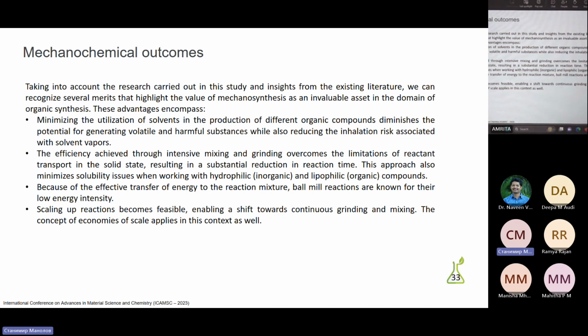The efficiency achieved through intensive mixing and grinding overcomes the limitation of reactant transport in the solid state, resulting in a substantial reduction in the reaction time. This approach also minimizes solubility issues when working with hydrophilic and lipophilic compounds, and because of the effective transfer of energy to the reaction mixture, ball mill reactions are known for their low energy intensity. Scaling up reactions becomes feasible, enabling a shift towards continuous grinding and mixing. The concepts of economies of scale apply in this context as well.